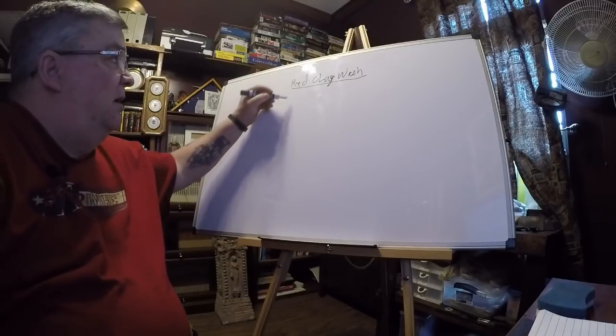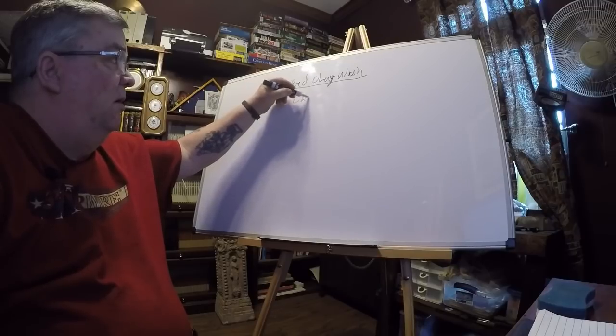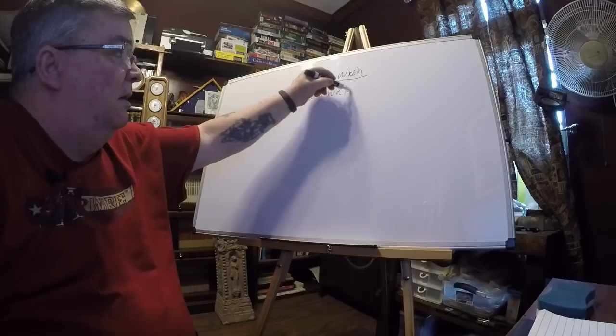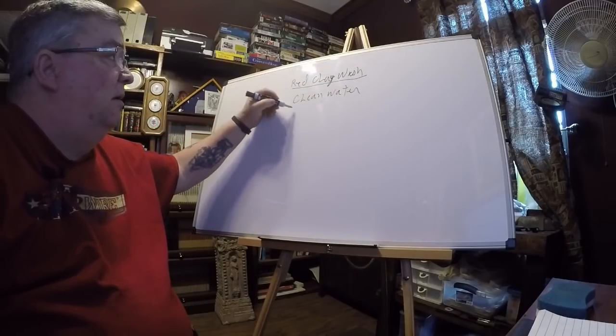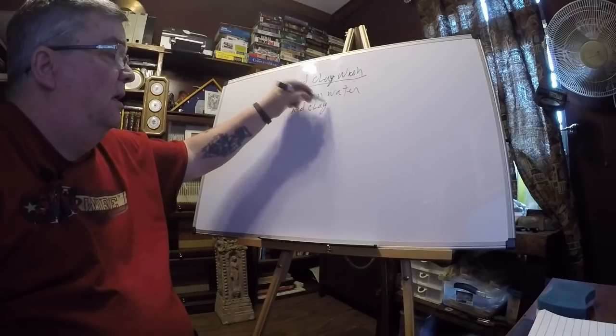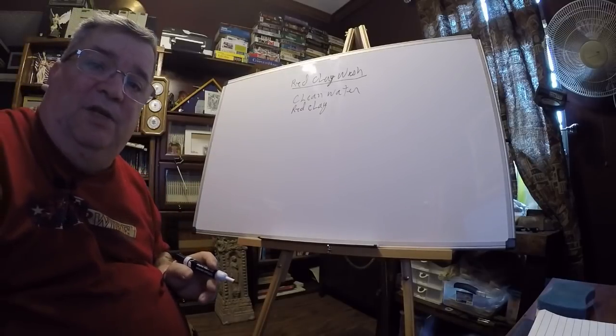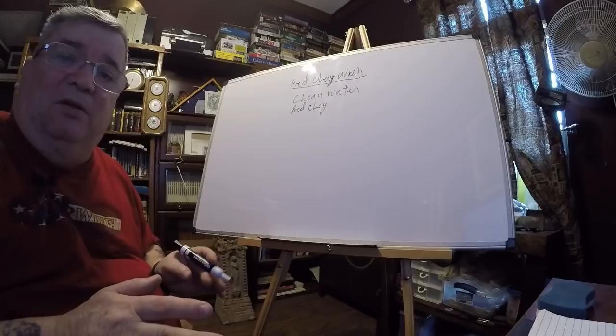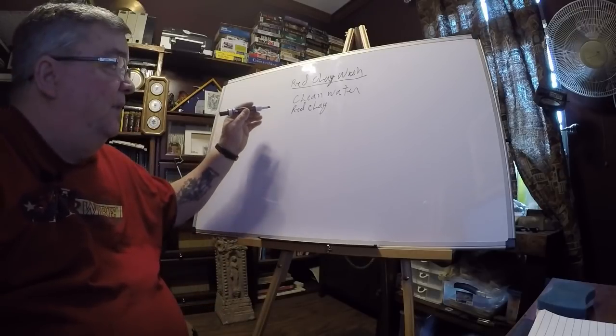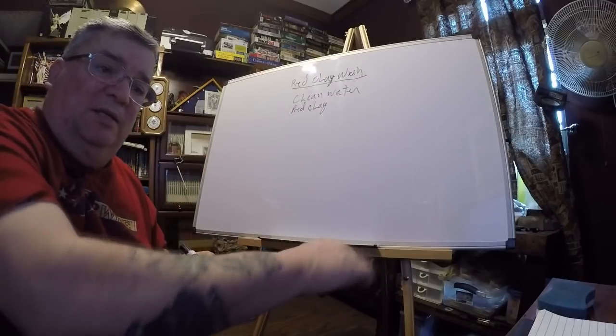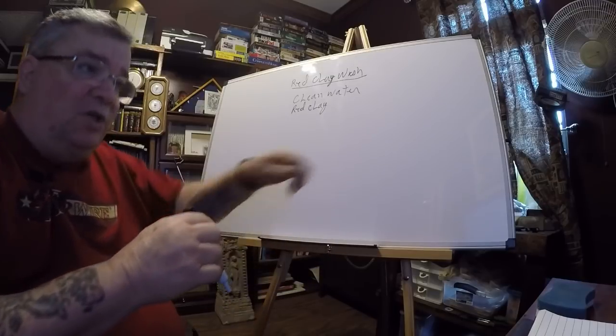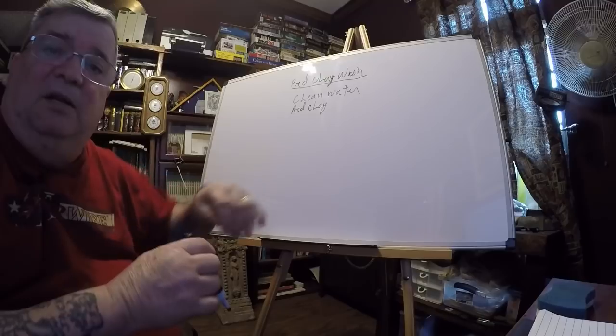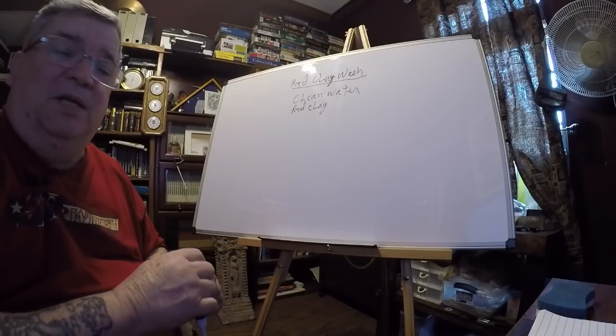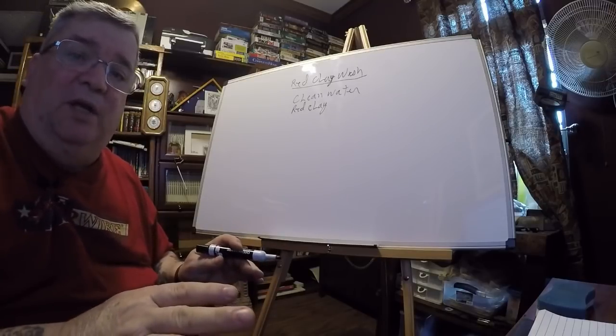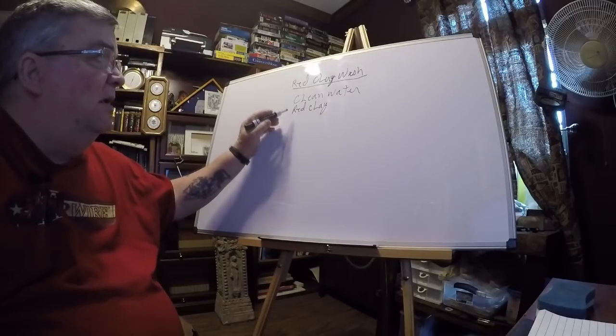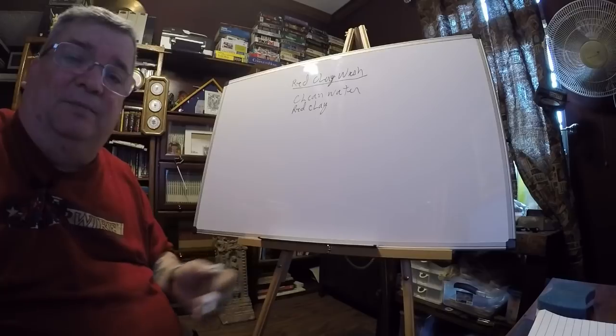Okay, just red clay. You take a container of clean water and add red clay; this readily dissolves in water. As with any material in nature, it's affected by water. So you take the red clay and squish it up in your hands, maybe sprinkle it in the water, and keep adding the red clay and stirring until the water turns red. As soon as it turns red, that's fine. You've got enough red clay in the water to act as a wash.